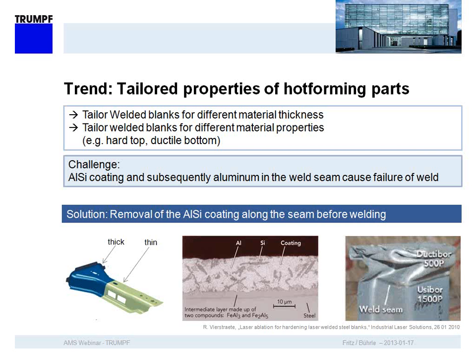So what they have to do is remove the aluminum silicon coating on the steel to be able to weld, or to get a good and strong welding seam. This layer is about 10 to 20 micron thick, and we can see here on the photo the thickness of that layer. This is a typical part with different thicknesses, and they have to be welded in 2D as a tailor welded blank, maybe also steels with different properties of hardness for crash properties.